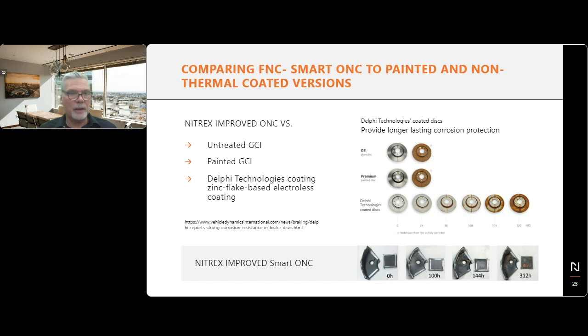And then you have Nitrex improved Smart ONC, which is of interest, zero corrosion at 100 hours, which is already better than the zinc coating somehow, and displays some corrosion at 312 hours, which is comparable or better than a zinc flake coating.